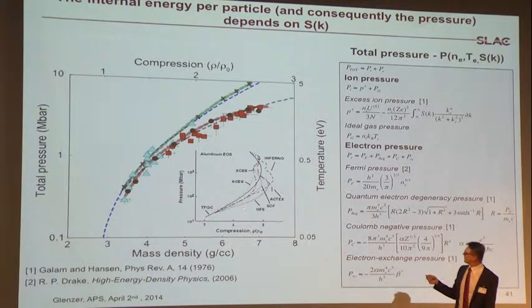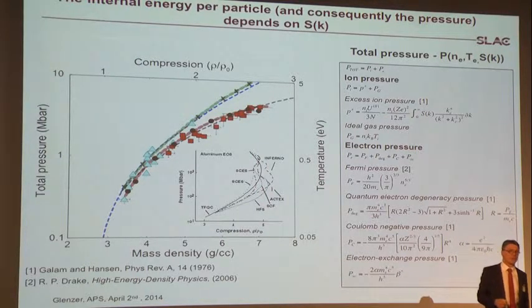Namely, what is happening here between compressions 4 and 5, ionization starts to set in of the K-shell electrons and the other 2p electrons. And what is happening is the material pressure is directly being affected. So, of course, this asks for a bigger laser to actually apply these techniques to test these predictions that are out there now for more than 2 decades.